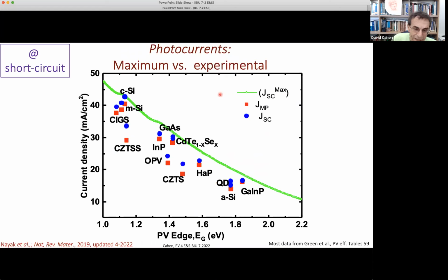We can first look at how the solar cells that we talked about do in terms of their theoretical current that they can give, which is the green line here, instead of the one that I showed before, but it's the same line, same calculation. At short circuit, there are the blue dots, and at maximum power for the existing best solar cells that I gave you before in the table to make an impression how inefficient solar cells are. So see, silicon is amazing. It has nearly 99% at short circuit of all of the photons that can be absorbed converted into electrical energy. Gallium arsenide less so.